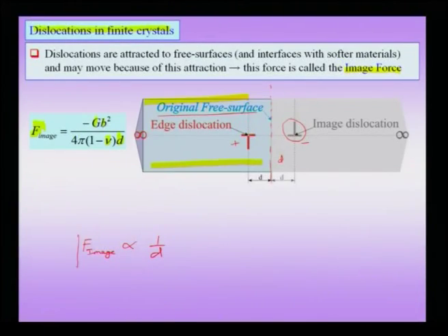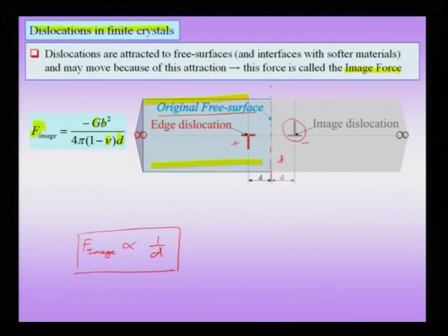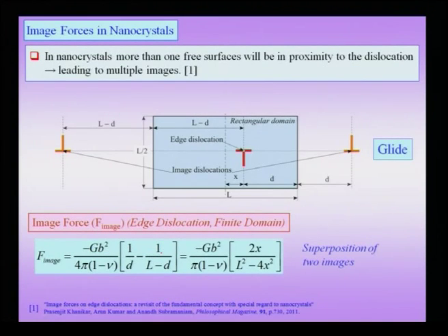Nevertheless, we now concentrate on the force, and notice that when a dislocation is positioned in a semi-infinite crystal, it feels a force towards the free surface, which is called an image force. And the value of the image force gets more and more intense, because it goes inversely with d as the dislocation is positioned closer to the free surface.